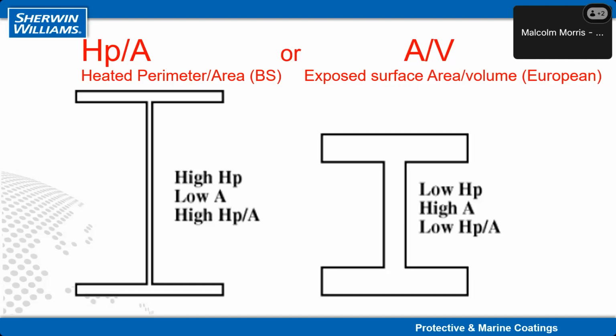They measure what's called the HP over A, which is the heated perimeter, the outside length, if you like, of the steel divided by the cross-sectional area. Comparatively, on the European standard, they measure the exposed surface against the overall volume of the steel, so that's the A over V. It's the same sort of concept, but slightly different numbers, and the European method, the A over V, gives a more conservative figure. You actually have to put more paint on to give protection on the European standards than the British standards, and the industry is moving over more towards the European, so the British standard will probably disappear very, very shortly.